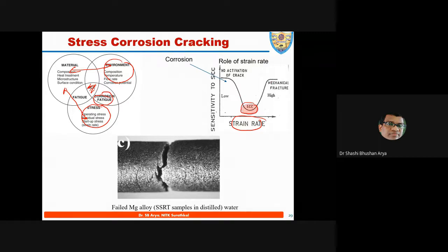But stress corrosion cracking will take place at a very low or optimum strain rate. Otherwise, you cannot detect it. So suppose this is your metal, and you pull from here and here by the sigma, a small crack will propagate. That's why material under this condition will fail very fast, because corrosion and tensile stress create the biggest failure for this material. So this is one of the magnesium alloys that typically fails during the test, because even distilled water is dangerous for magnesium alloy.